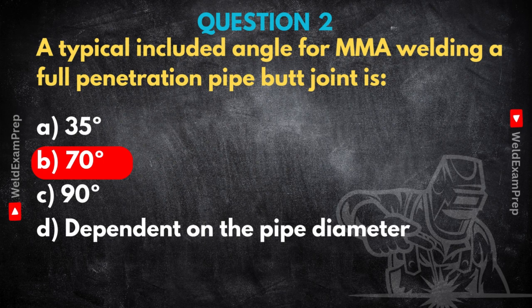You'd risk lack of fusion on the sides, maybe incomplete penetration, or trapping slag because the molten slag just can't get out easily. That's a big one. On the other hand, if the angle was way too wide, say 90 degrees or more, well, you'd need a lot more filler metal. That means more welding time, higher material costs, and it significantly increases the risk of distortion because of all that extra heat input.